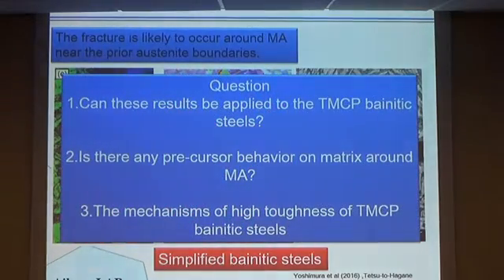But there are some questions. Can these results be applied to the TMCP bainitic steels? These research experiments were conducted using steels which have a very simple microstructure. But the usual TMCP bainitic steels have a very complex, very fine microstructure. And second, is there any precursor behavior on matrix around MA? And third, what is the mechanism of high toughness of TMCP bainitic steels?